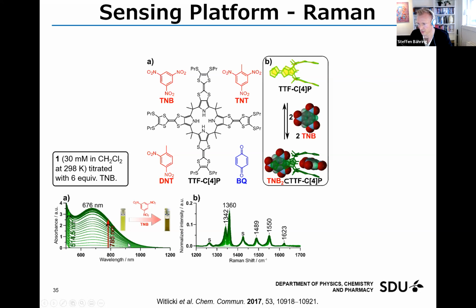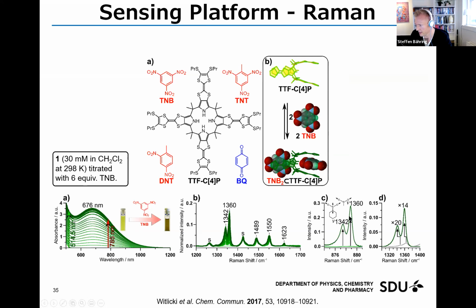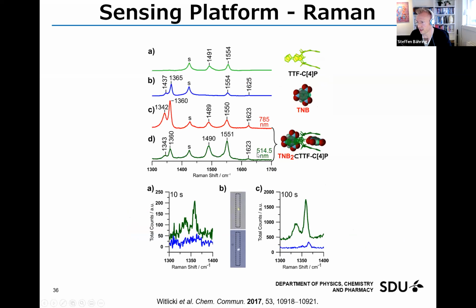And you can see here that during the titration with adding in TNB, we have an increase in the CT band, and we have an increase in the Raman scattering of the nitro groups of the TNB molecule. And here it's more evident that when switching from 514 nanometers to 785 nanometers, we have an extreme increase in signal for these nitro vibrations of the TNB molecule. So here we showed that we're able to make a fingerprint of the TNB molecule when it's complexing the calix[4]pyrrole, so we can avoid other contaminants that don't absorb in this area. But the combination of the explosive binding TNB will increase the Raman scattering at this wavelength.